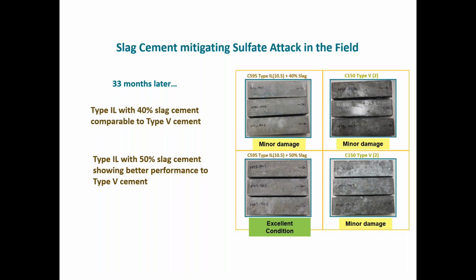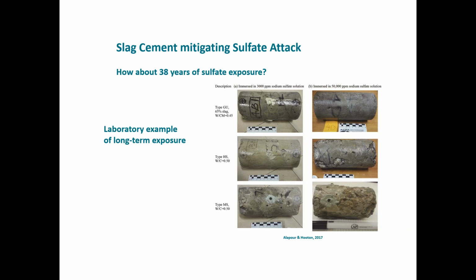So next slide. I think this is my last one. I know we're running a minute over, but if 33 months isn't enough for you, now this isn't a field exposure, but I thought this was a great way to end this discussion, in that what can slag cement do over the long term for durability? Starting at the bottom, you're looking at an MS cement. So this is a moderate sulfate cement, the equivalent of a type 2 at a 0.5 water cement ratio. You're looking at an HS, which is the equivalent of a type 5. And then you're looking at a GU cement, and I meant to incorporate the notes, but you're talking about a GU cement that has something like far above 8% tricalcium aluminate.